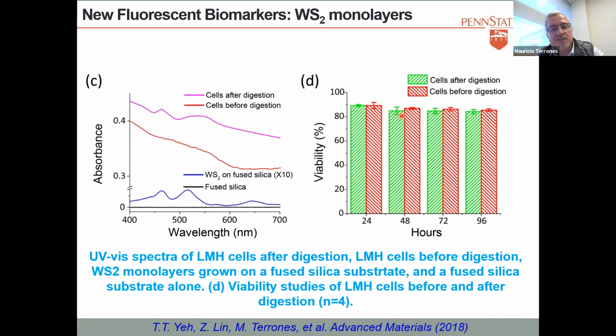And then we check the cell viability. So we see, is it very harmful for this type of cells? Maybe because the cells can die, right? If they ingest something that is not good, they can die. In this case, the cells we tried were not making much change, right? So the cells after ingestion are the green ones, and the cells before ingestion are the red ones. So basically they are very comparable. So that means that this is a system that can be used in the future.